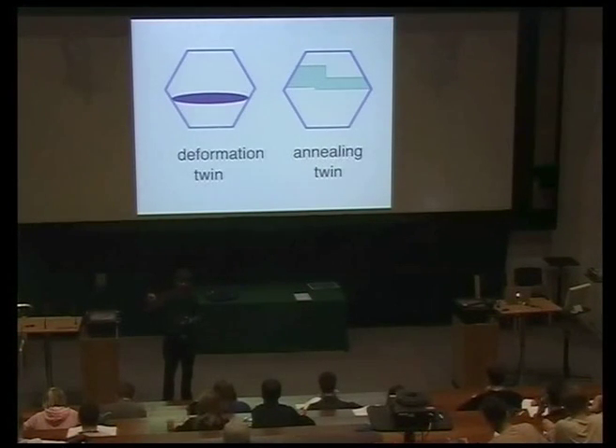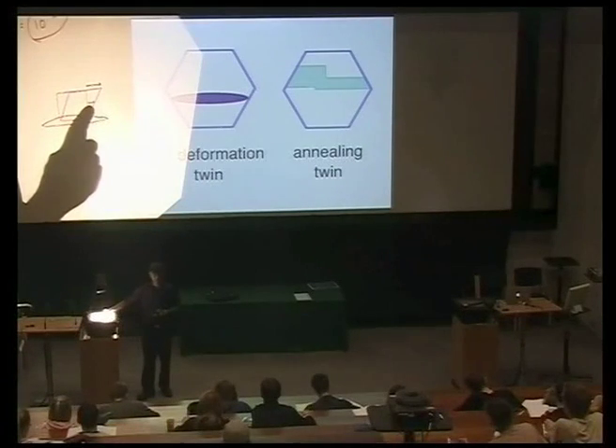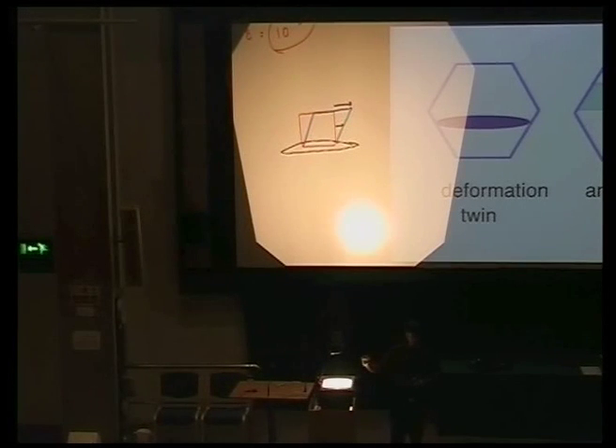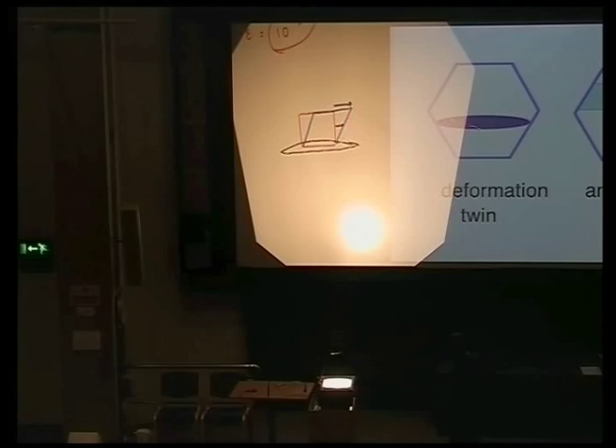That's why a mechanical twin will always look like a lens shape — in three dimensions, a lens with a very sharp tip at the end, because then the displacement is minimal. If you make the tip extremely sharp, that displacement is more or less zero. So it's favorable for this to be a very thin plate. Whenever you see in the microstructure a lens-shaped object, that really is to minimize strain energy, and if it is twinning you can identify it by that shape.